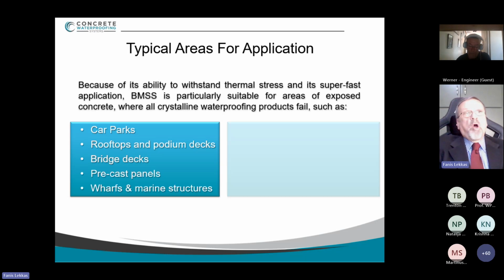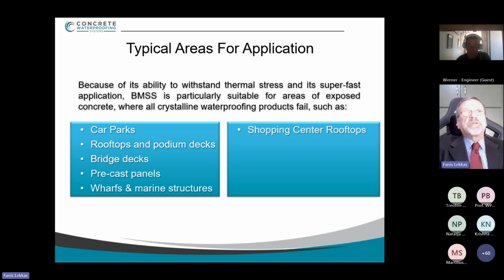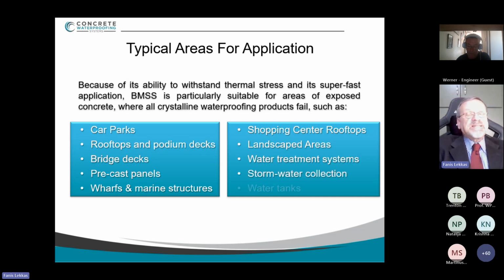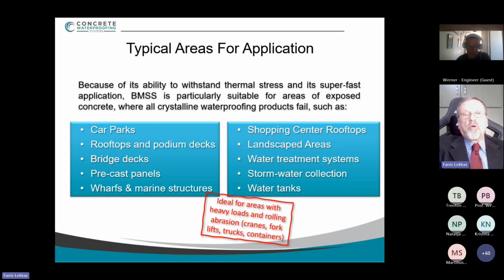This technology also allows the concrete to accept thermal stress up to 160 degrees. Imagine that after you treat concrete with this technology, you can apply hot asphalt of more than 160 degrees directly on the concrete without first needing to protect it against thermal stress, without a protective layer, topping, or a screed. So think about it. You can apply up to 6,000 square meters in 1 day with one person, and it can even accept hot asphalt.